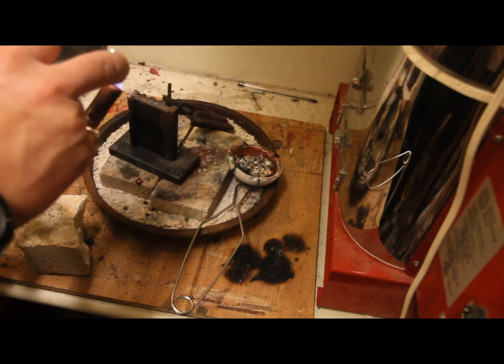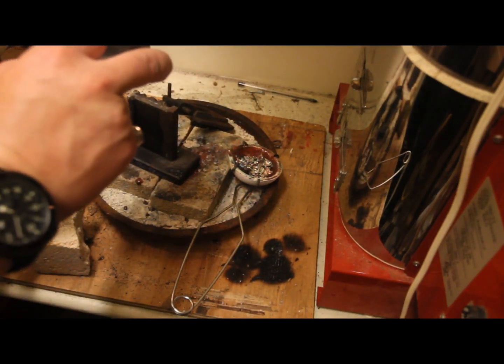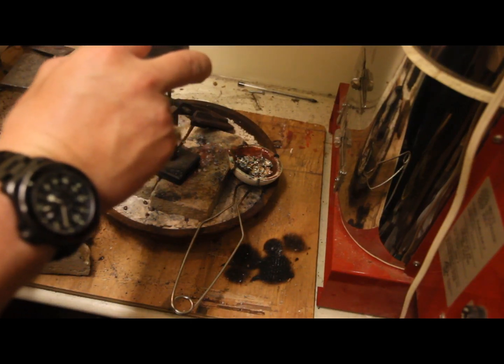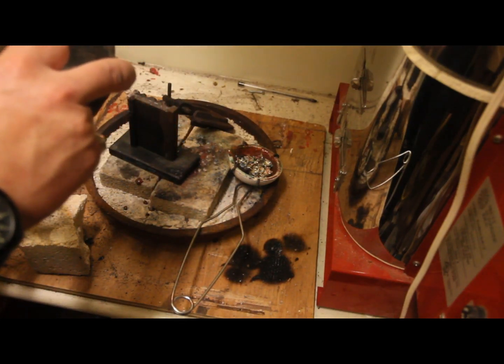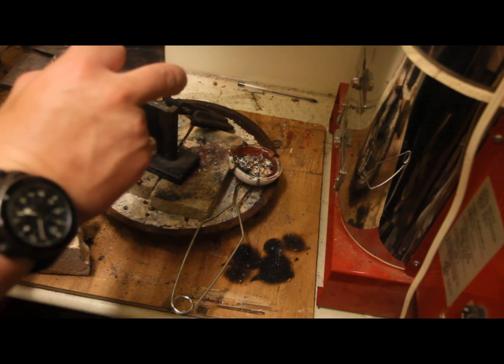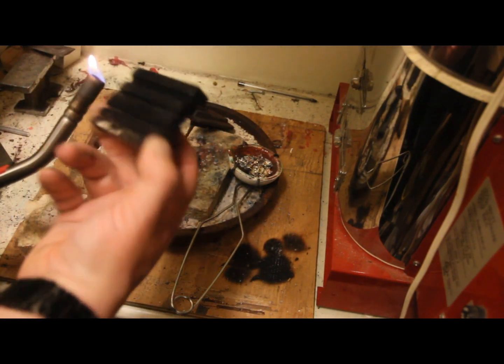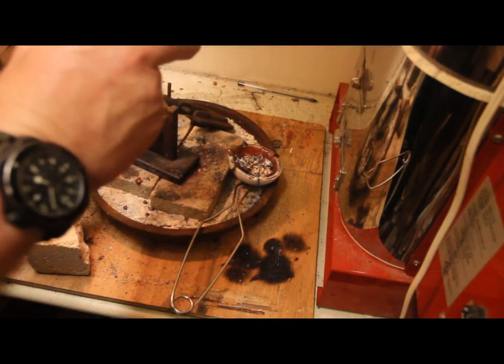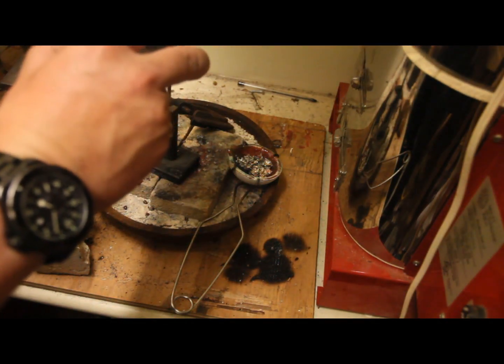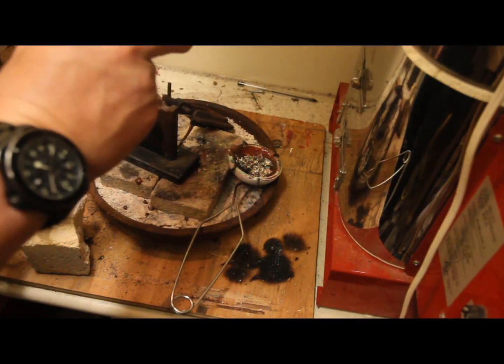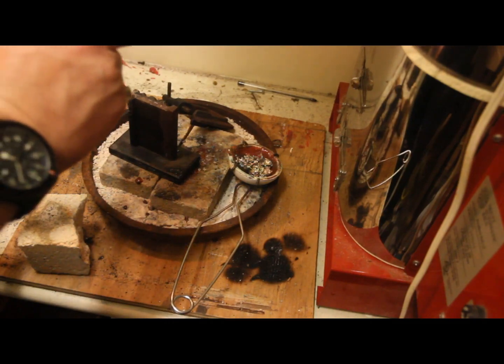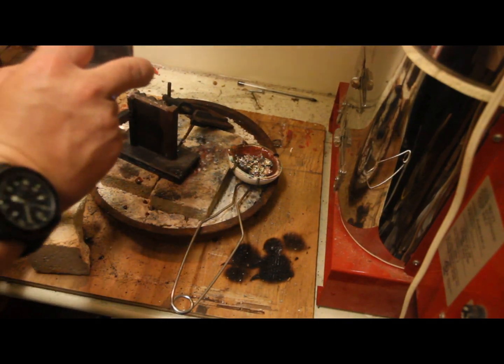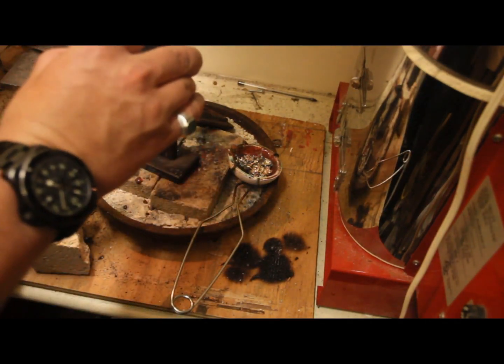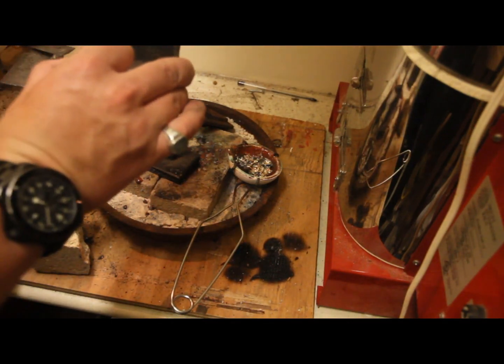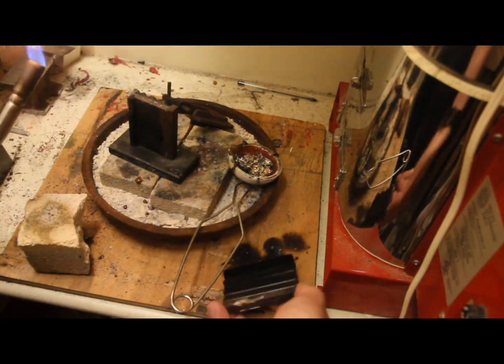At the beginning here, what you'll see me doing is using an oxidized flame, that's that orange flame, to put a layer of lamp black or soot on my ingot mold where the silver is going to flow through. That's going to stop a big buildup of air bubbles inside the ingot mold whenever I go to pour the molten silver in, and it's also going to stop the silver from sticking in weird places and causing deformities in the ingot when it's all said and done.